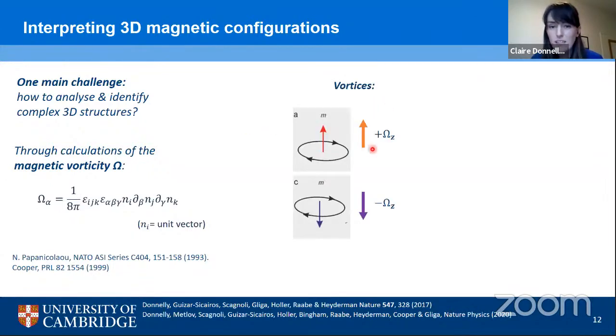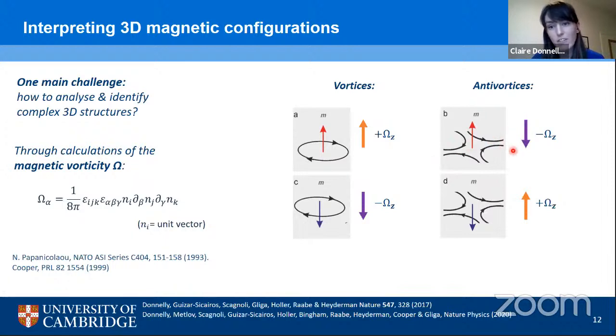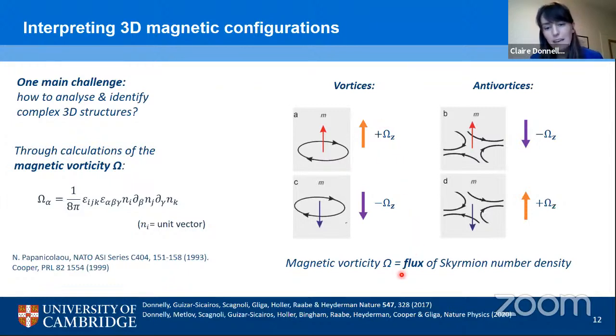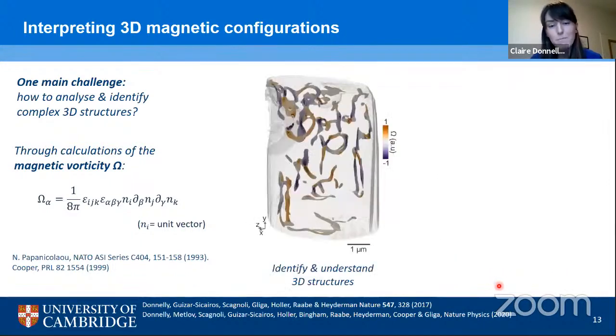When we think about vortices, we see that the vorticity vector aligns parallel to the core of our vortices. For antivortices, the vorticity vector aligns antiparallel, reflecting the opposite topological charge of a vortex and an antivortex. And indeed, we then have this understanding that the vorticity vector is the flux of the skyrmion number density and directly related to the topology of our magnetic configuration. So we can use this to actually identify topological features within our data set. We do this by plotting regions of high vorticity within our pillar.